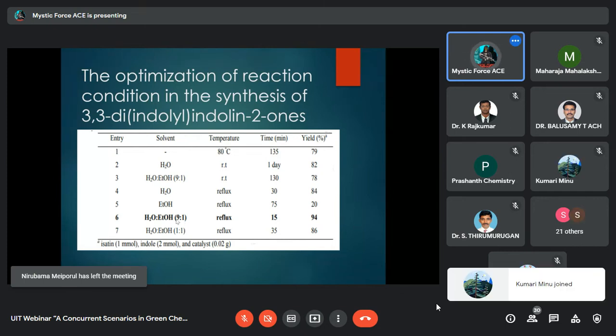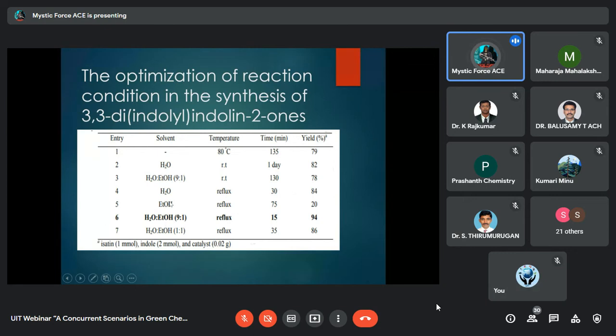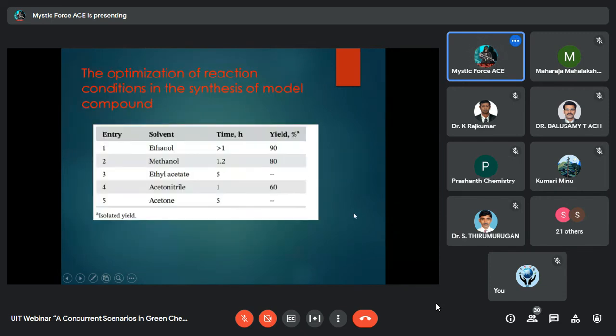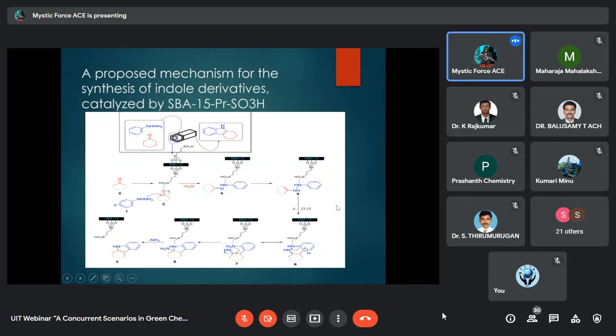And if we do the same reaction, water and ethanol, as I have told, 9:1, here it was room temperature, here it is in reflux condition. So when this was in room temperature, time was 130 minutes, but now you can see time decreased to 15 minutes and reaction yield increased to 94%. So this is again the optimization reaction condition of synthesis of model compound. Ethanol, time was more than 1 hour and the yield was 90%. So what we have done, this is the mechanism of this reaction.